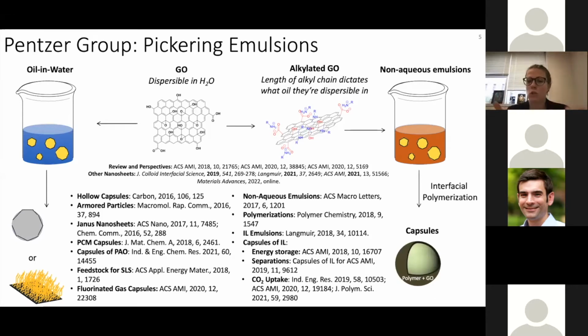And if you want to stabilize a non-aqueous emulsion, typically you end up making a block copolymer in which you have to carefully tune the Hansen solubility parameter of the blocks, as well as the relative ratio of the two blocks. But here we're just alkylating the nanosheets to get them to be interfacially active. And so I'll talk a bit more about this, but from the standpoint of, we now have access to systems with a controlled amount of water. So they can be water-free, or they can have a controlled amount of water present.